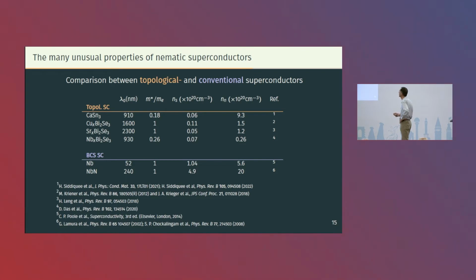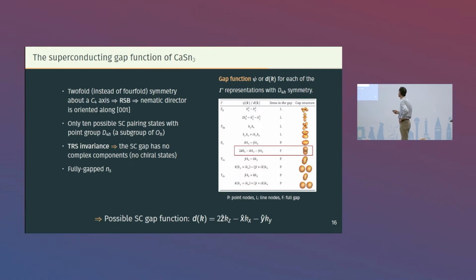Here, this Hc2, here we have 1,600, or these very, very large numbers. And also what is important is the huge difference between the normal state electron density and the superconducting electron density. Here they are different, but not so much different. Here it is extremely different. So they are really a different class. You can really touch it by hand. Now the question is, what does it mean?